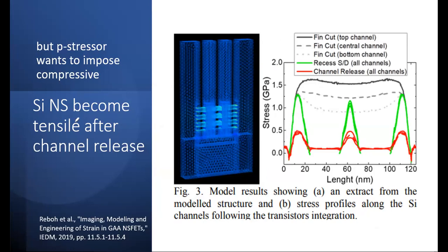The silicon nanosheet actually is formed differently than the FinFET. FinFET initially, when you cut it, is like in free space, right? There is no strain. But silicon nanosheet is formed by removing the SiGe layer here, because initially they are tensile strained. Let's keep it in mind. So when it just forms, it's actually tensile. Positive value means tensile. They are not compressive. So then you need to form a source-drain ring around it in a way to make it compressive. Initially it's tensile, so you need to do more work for your stressor, right? And your stressor right now is more defective. That's a big problem, right?